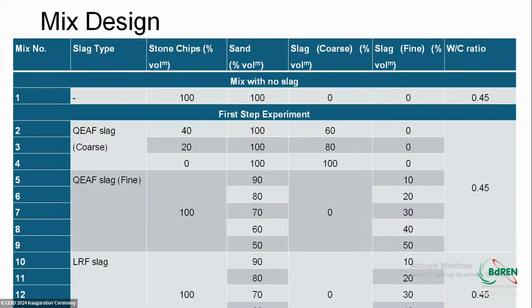And then we used different mixes. In our first trials, we used no replacement of stone or fine aggregate, and then we replaced with EF slag - we used 60% to 100% slag in replacement of coarse aggregate. For fine aggregate, we replaced 10 to 50% of sand with EF slag and 10 to 30% of sand with LRF slag. In all cases, we kept water cement ratio at 0.45.